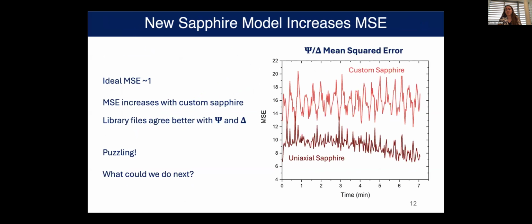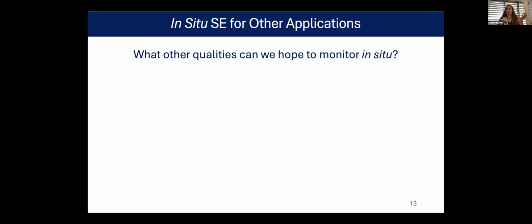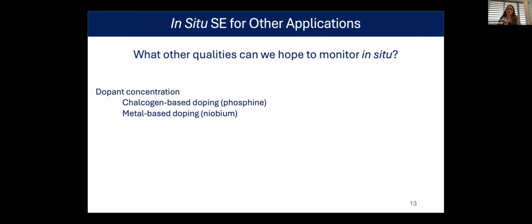There were some issues where we saw a higher mean squared error between the predicted psi and delta and the data psi and delta. So that's the current issue that I'm trying to resolve, is understanding how the sapphire is behaving and why we might get a more accurate coverage, but a less accurate psi and delta fit. So this is my priority, because if we can figure this out, we can look at other potential applications where, if I can have a model for different dopants, then if we were to p-dope or n-dope the films, I could get a live coverage concentration of what the dopants are.